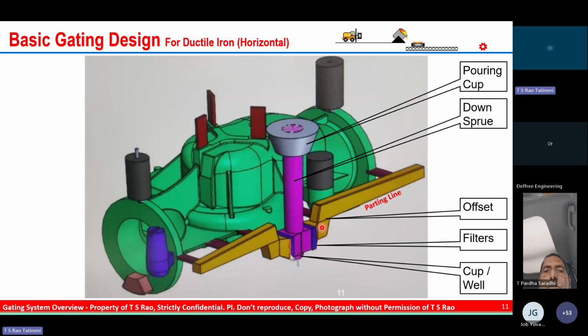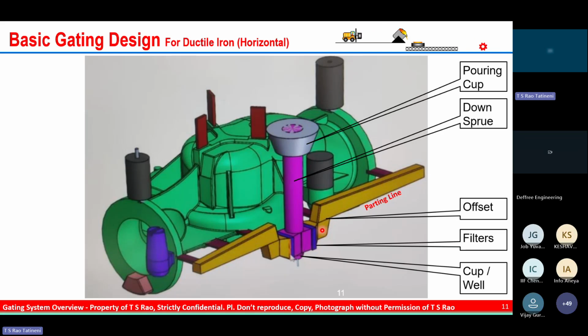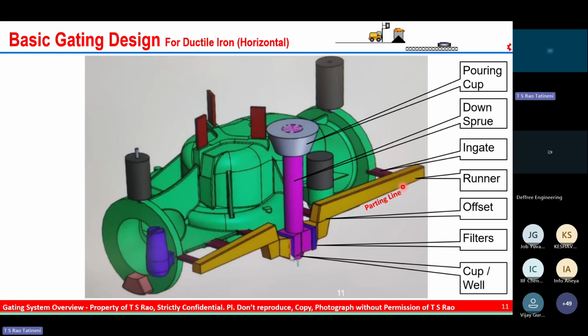Next one is the offset. As I said, the offset is very important when the metal goes. Normally, when you pour the metal, we pour in the cope half, and this is the parting line. The metal comes to the drag half, then the metal gets filtered, then clean metal travels to the cope half. So that's why this offset is very, very important to ensure that there's no turbulence and the metal goes with a laminar flow through the runner bar. Then followed by the runner and the ingates.